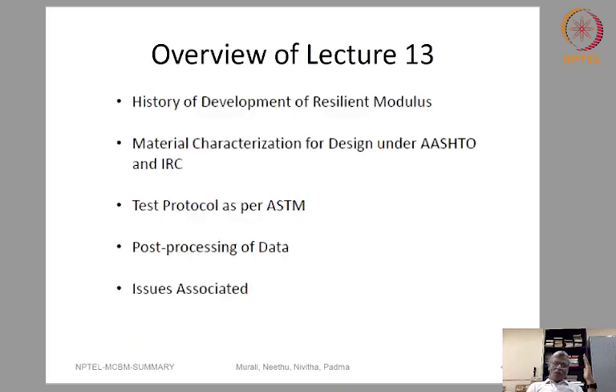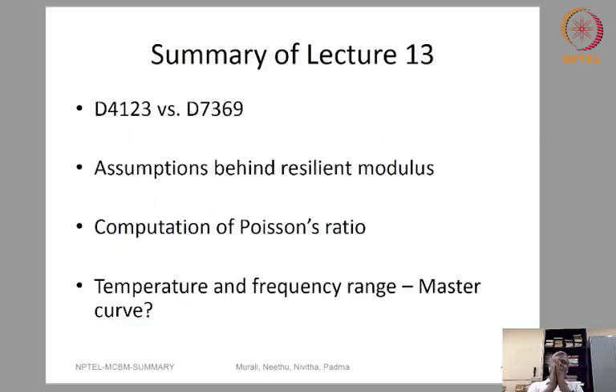So Dr. Neetu Roy gave a history of the development of resilient modulus, material characterization for design under AASHTO and IRC. She gave the complete difference and the test protocol as per ASTM and post-processing of the data and issues associated with it. So the summary is, there was originally a standard ASTM D4123 in which you made measurement only in the horizontal direction, and then you used it to compute the resilient modulus. No measurement was made in the vertical direction also. So most of the time the Poisson's ratio was just assumed. In ASTM D7369, you not only make measurement in the horizontal as well as the vertical direction, you also do it on either side. In addition, you also rotate it by 90 degrees.